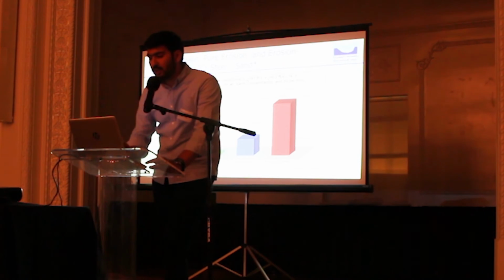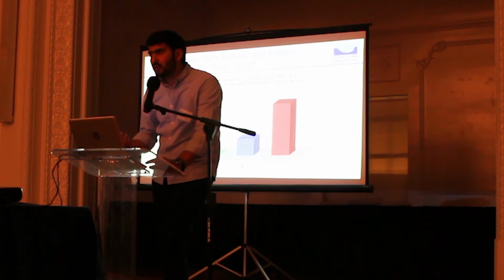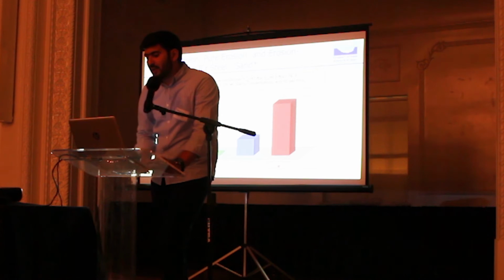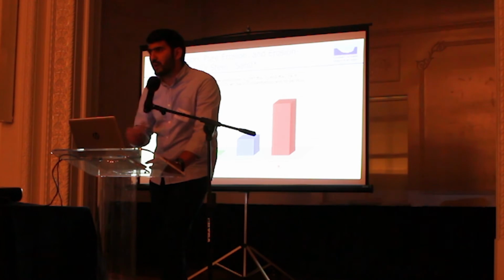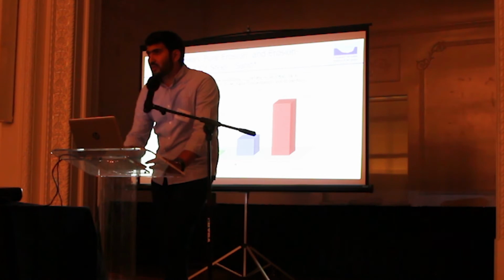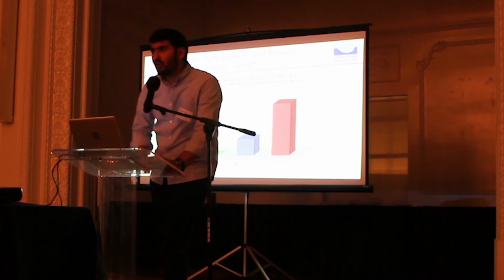The vertical axis represents the penetration rate in mils per year. The first column from the left represents pure corrosion. Then we have pure erosion, so it's just the solid particle erosion action here. And then here we have erosion corrosion, the combined effect. As we can see here, erosion corrosion does not give exactly the summation of pure erosion and pure corrosion, suggesting a synergistic effect, or synergism, between erosion and corrosion for 13 chromium steel under these environmental conditions.